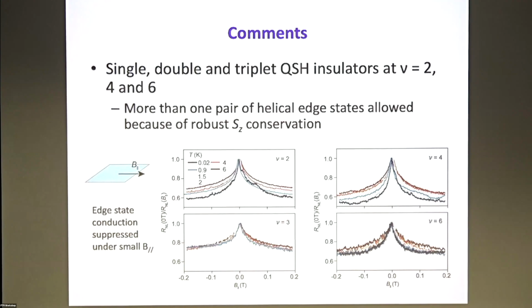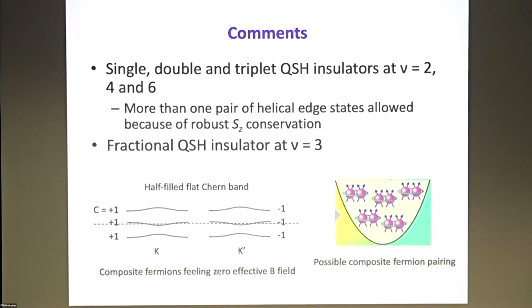That is for all the incompressible states at integer fillings. But if you do the same thing for the compressible region, the in-plane magnetic field would not do anything. For the filling factor 3 state, we think it's a fractional quantum spin Hall insulator. This is the band structure. It has a series of C equals +1 Chern bands at the K valley and a series of C equals -1 at the K prime valley. They are very flat, almost like Landau levels. So nu equals 3 corresponds to a half filling of 2 Landau levels of the second flat band. So they pair, possibly indicating some kind of composite fermion pairing.